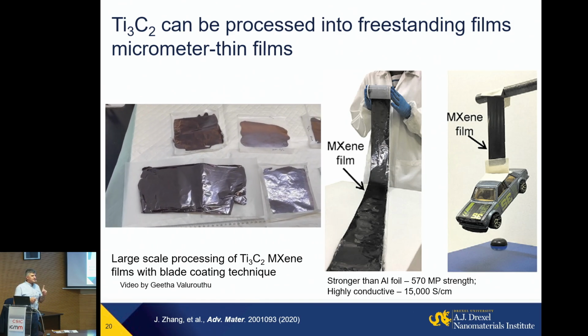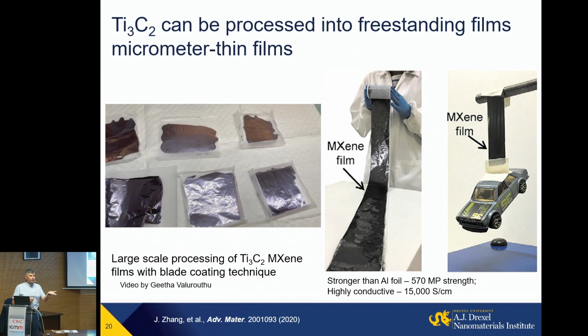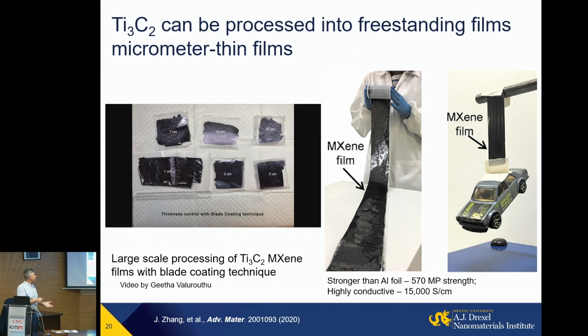This film is 1 micrometer thin. It's 10 to 20 times thinner than aluminum foil, the metal foil that people use. But it's highly conducting. Moreover, it has a strength exceeding the strength of aluminum foil. Aluminum is between 150 and 500 megapascal. So you can make freestanding, very strong membranes, films, for a variety of applications. You cannot easily process metal to the same thickness, and it's still highly conducting just after drying.